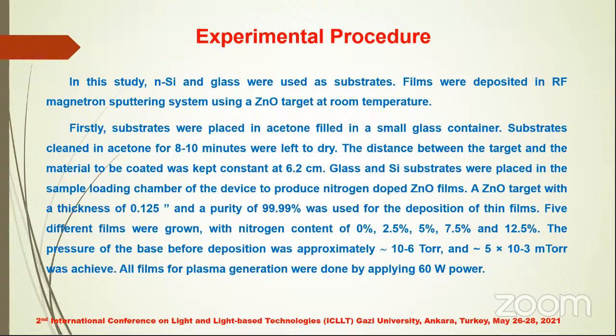The base pressure before deposition was approximately 10 to the minus 6 torr, and a working pressure of approximately 5 times 10 to the minus 3 millitorr was achieved. All films for plasma generation were done by applying 60 watts of power.